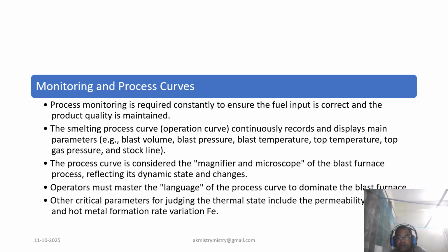Operators identify asymmetries by checking parameters like differences in top temperatures, heat losses, and variations in hot metal temperature between tapholes. We rely on smelting process curves which continuously record key parameters like blast volume, blast temperature, and stock line. Mastering the language of these dynamic process curves is described as necessary to dominate the blast furnace operation.